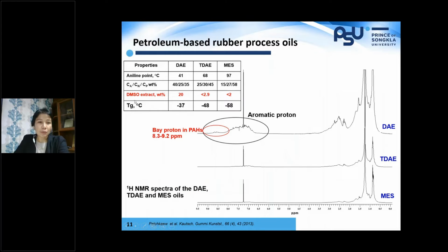And by changing the type of oil from DAE to TDAE or MES, please be aware that because of different composition, we can see from the different ratio of aromatic carbon, naphthenic carbon, and paraffinic carbon, they are different. And this different composition and of course structure, this oil has different glass transition temperature. So when we add this kind of oil into rubber compounds, we also expect that the dynamic mechanical properties of those compounds will also be affected.